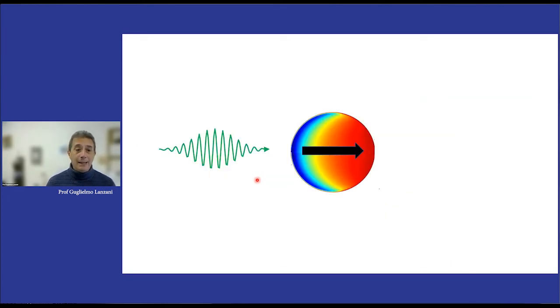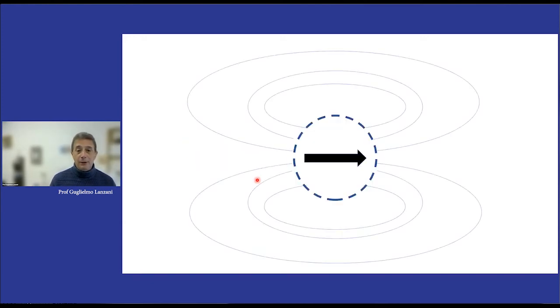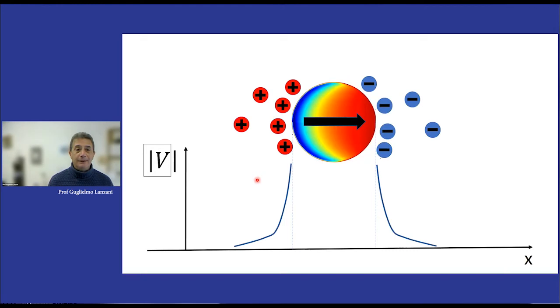Now, let's assume light comes from the left, and it is generating this dipole, as we saw. Okay, then the dipole has certain field lines, so lines of force in the space, and that's the field. Now, if there are ions around, those ions will move and screen the field. So the negative charge will appear here, and the positive charge will appear here. And they will screen the field within a distance, which is given by the Debye distance. And the Debye distance for this concentration of ions is extremely small. We are talking about a few nanometers.